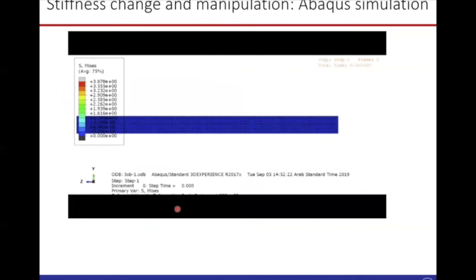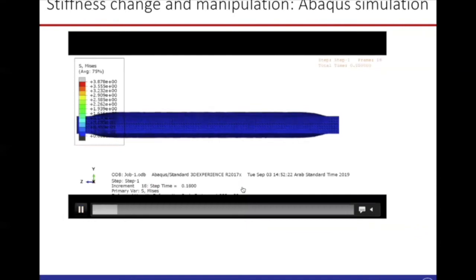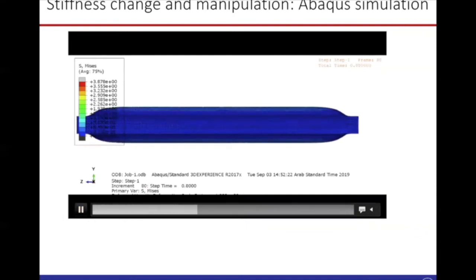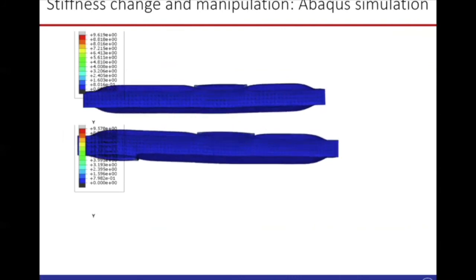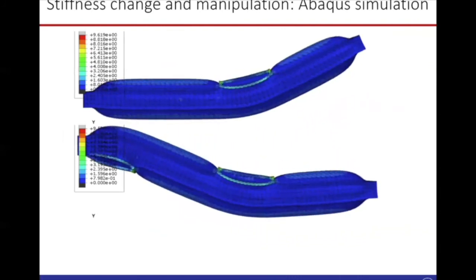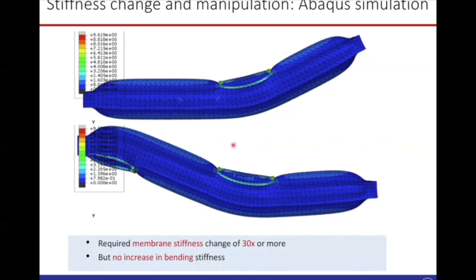So before going into detail, first we did an Abaqus simulation here. You can see a single chamber which expands in all directions, where its stiffness is the same everywhere. But as you introduce some stiffness asymmetry, it could produce some complex motions. Here, the fiber is stiffer than the skin, and it prevented the deformation between these 2 points. We used around 30 times stiffer than the skin of the actuator.